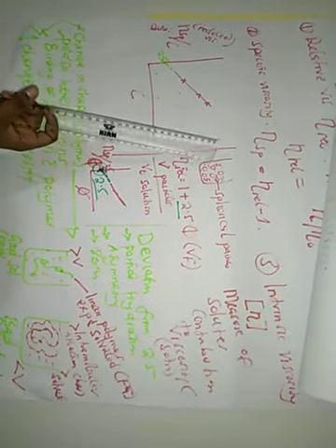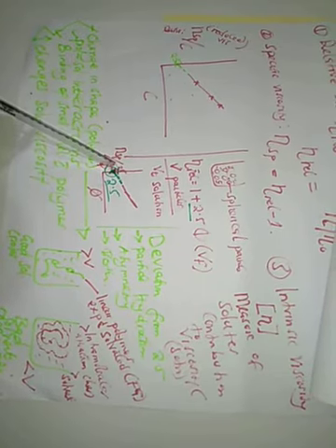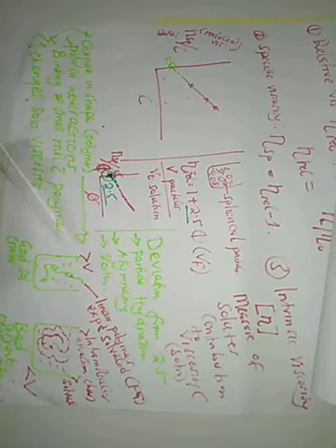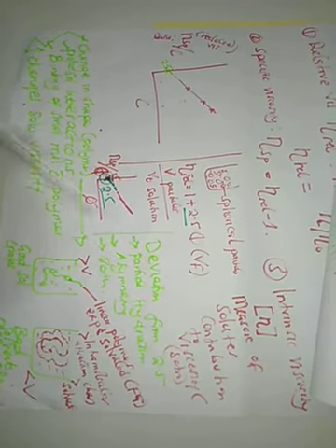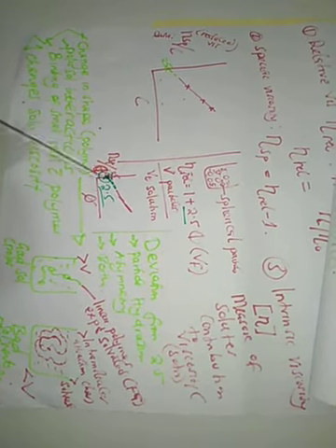Now, if there's any deviation from this value, as long as a polymer is forming spherical particles in solution, if there's any deviation from the 2.5 after you plot your graph, there are two explanations. Either your polymer spherical particles are becoming hydrated, so it's due to particle hydration, or particle asymmetry. Particle asymmetry simply means your particles don't have an equal shape and also size. So there's particle asymmetry and also particle hydration. Sometimes it can be both factors, so both these factors can result in deviation from this value.